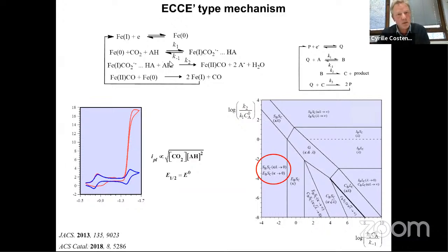And then with a second water molecule, you actually break the CO bond, and with this water, you get iron 2 CO, which is then reduced either at the electrode or by iron 0 to get iron 1 back, and with this CO. And so here is the formal mechanism, where you have a catalyst, then a pre-equilibrium, then an irreversible process, and then a fast reduction.